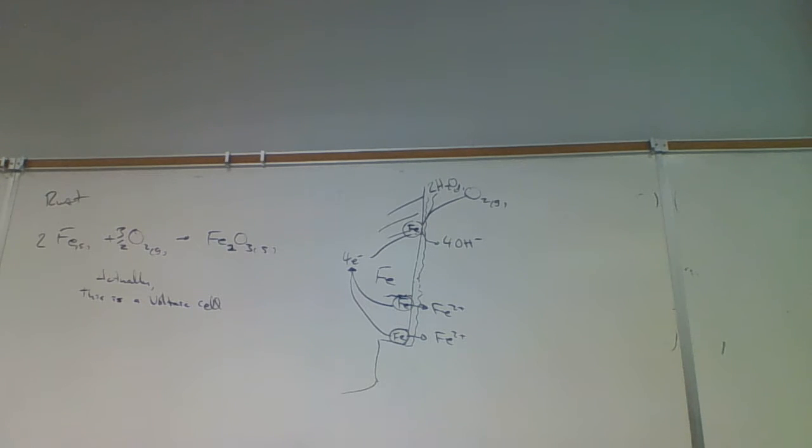Well, what if we wrap zinc foil around it? If we wrap zinc foil around the nail, then take a look. This is a pristine nail. And so it looks like the iron is the cathode, like it was before. But what's the anode? The anode is now zinc. You see? The zinc is being corroded. In fact, do you see white zinc hydroxide precipitate here? Well, you can see it in your book. There's white zinc hydroxide precipitate around this. In other words, zinc has a higher oxidation potential than iron, and therefore the zinc is going to be oxidized.